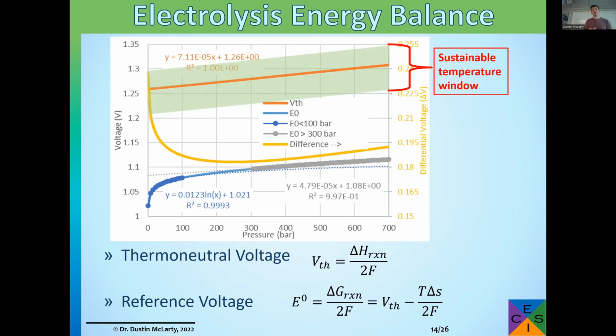So the yellow line is showing how initially, as you pressurize a little bit, that voltage potential you have drops significantly, but then it levels off and actually begins to increase a little bit towards the end. So it goes from around 240 millivolts down to, at really high pressure, around 190, 195 millivolts. So it's a little bit of a drop in your voltage potential, but you can recover that by expanding that green operating window and getting to a higher operating voltage.